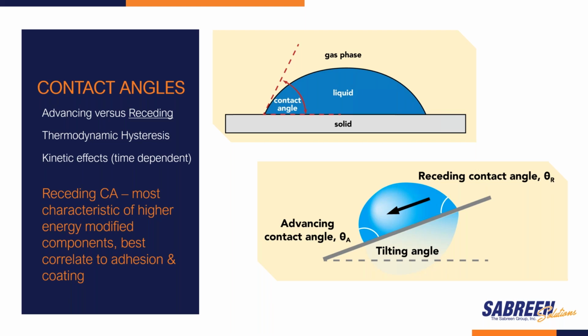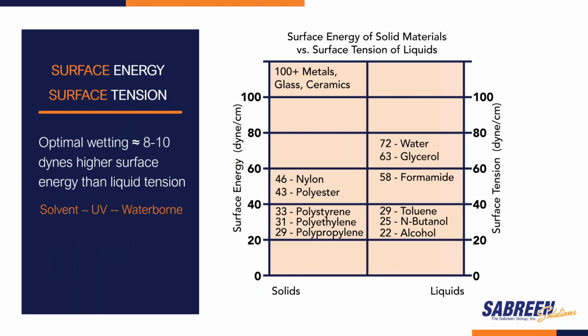On the other hand, the receding angle is actually the measurement most characteristic of the modified components of the surface following the pretreatment, as measured in the dyne solutions. So let's look at surface energy and surface tension.